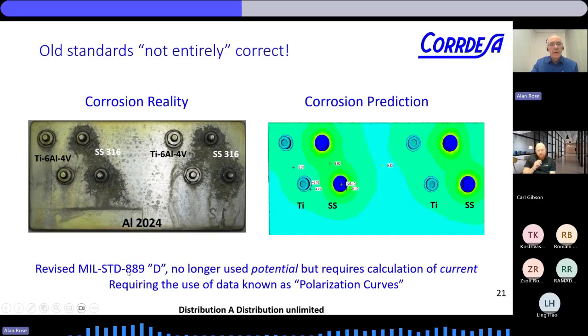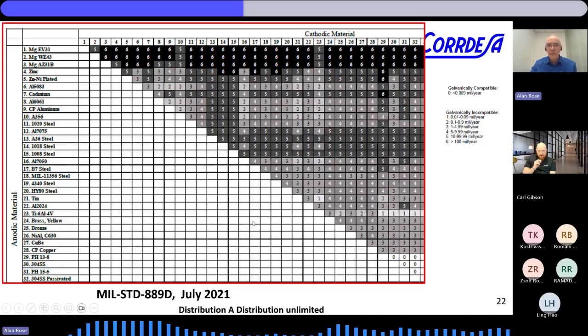So military standard 889D doesn't use potential anymore. It is a requirement to calculate the corrosion current, and they do this through the polarization curves. So what they did now is pre-calculate measured polarization curves for all these materials. This is in the standard, and it's just like in the old days before sat-nav. If you wanted to know how many miles between London and Manchester, you would pick one town on the left and pick a town on the right.